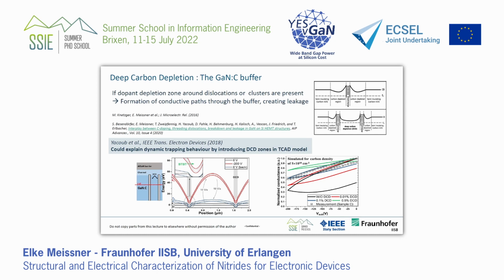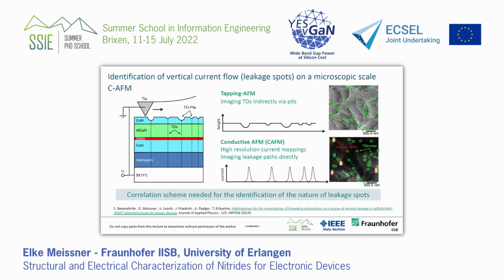And this was very encouraging for us to say, okay, the route that we have chosen is good, to look with this strategy that we have done. Then we went to AFM, and I had a very good PhD student who was doing it. And we said, okay, with the AFM we can measure very directly. Now we have learned what the dislocations may do. Now we go to a HEMT structure, we say there is a 2DEG, and we measure with the AFM tip in a vertical geometry, and we let the current flow between the tip and the backside.